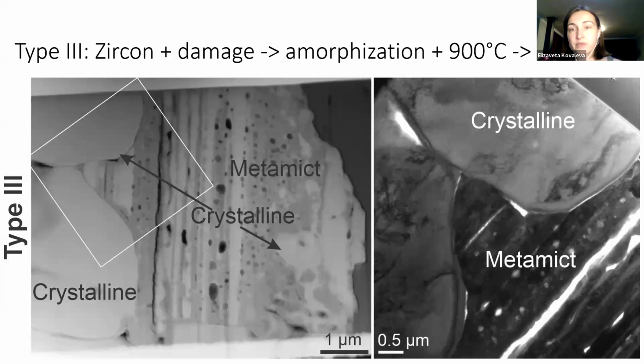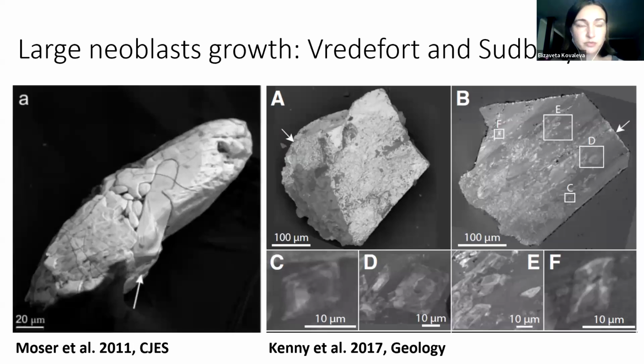in the solid state. And this darker material is amorphous, but it can also be shock amorphization. But in this example which I'm showing, this is radiation damage. And this was found in several impact structures. And it is believed that when this amorphous material is heated at about 900 degrees, you have these nice new neoblasts, and they're usually larger than the previous two types. These are two examples, one from Vredefort and one from Sudbury.